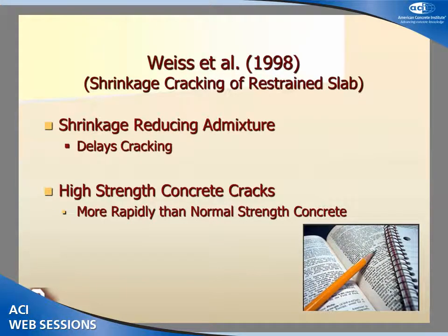And in 1998, Weiss and his group studied shrinkage cracking of a restrained slab, and he showed that the shrinkage reducing admixture delays the cracking, and high-strength concrete cracks more rapidly than the normal concrete.